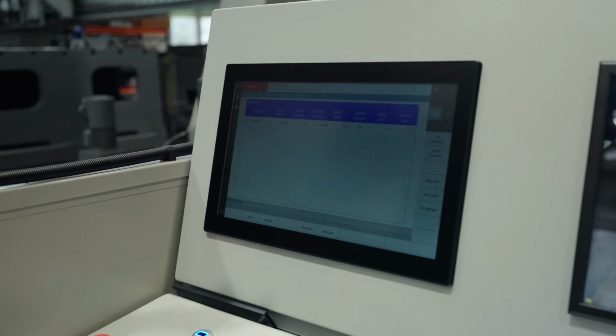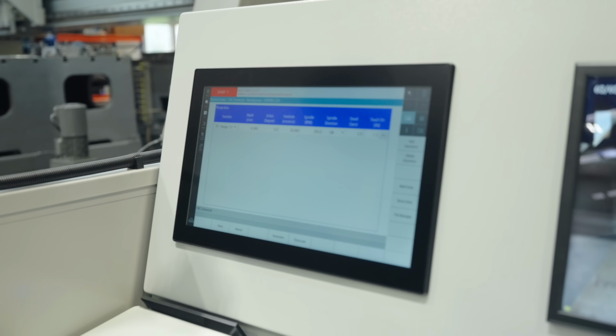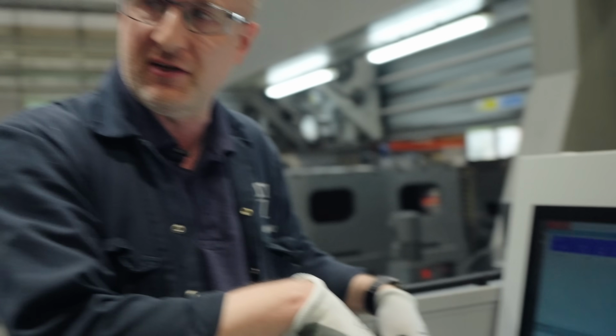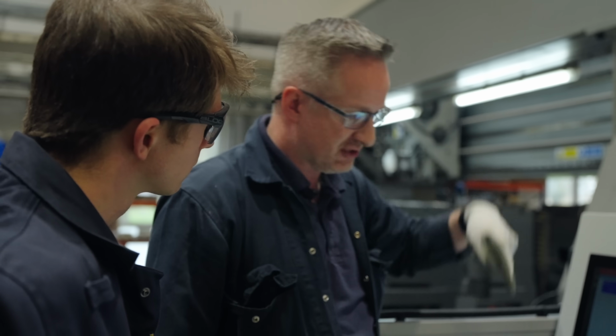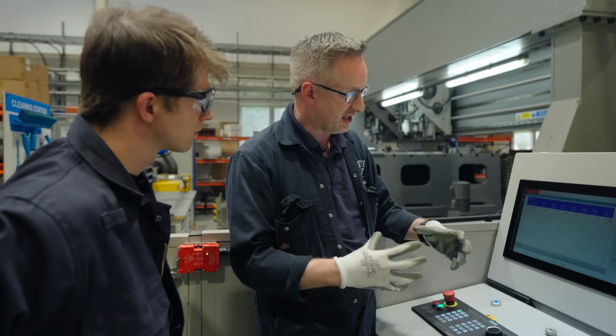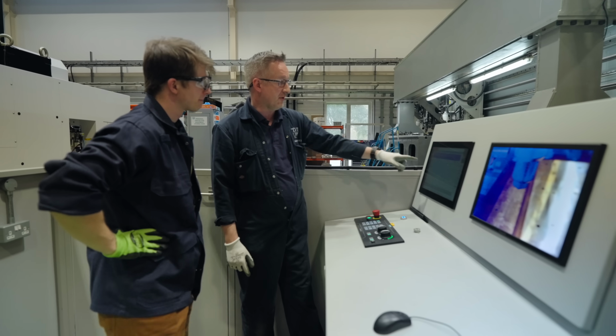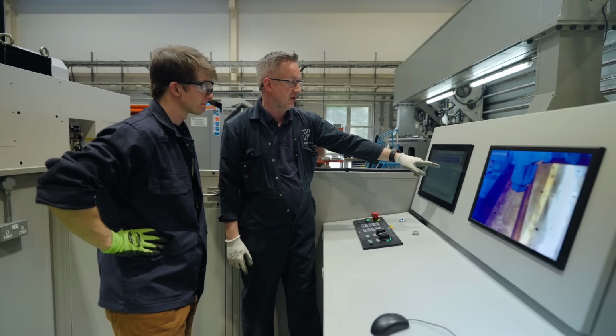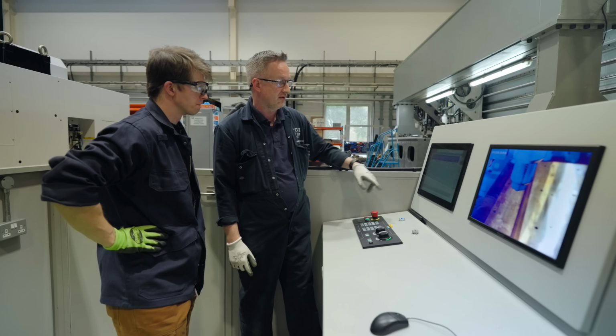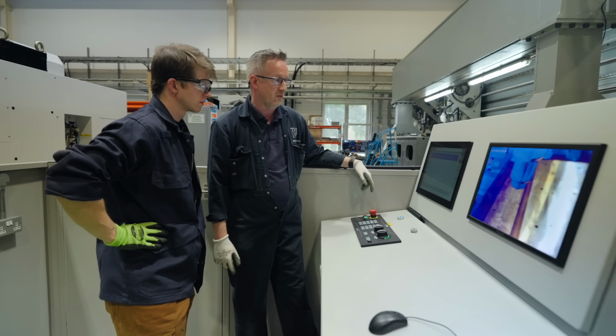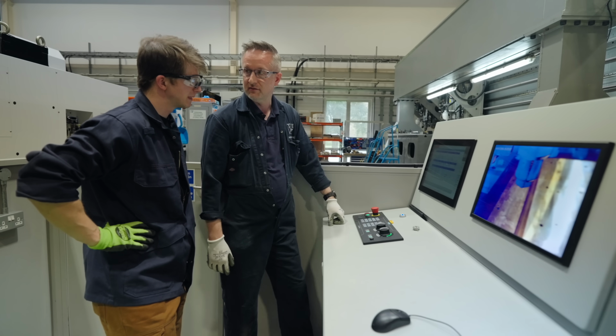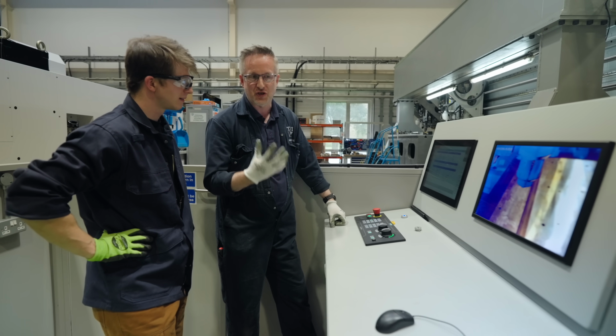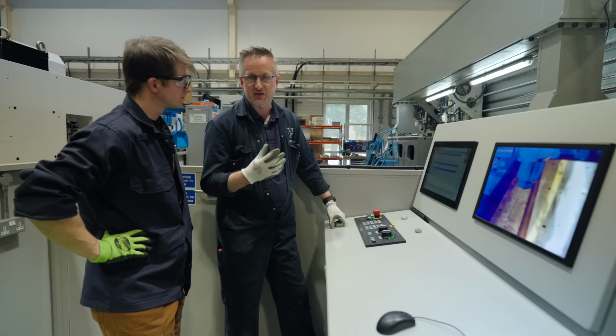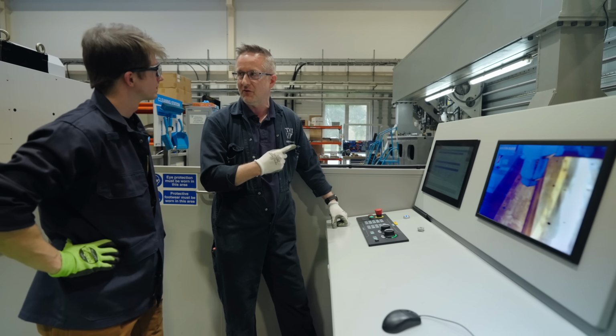Wow. So we just check our welding parameters. So we're going to plunge. We need to plunge at a rate of 20 millimeters a minute and a rotation speed of 250 into a set position, and it will dwell there to get heat into the tool and into the plate. And then we're making a weld of 230 millimeters long and a traverse rate of 120. 250 RPM. Not very fast. We don't want to make it too hot, because if we make it too hot, we'll lose the properties of our material.